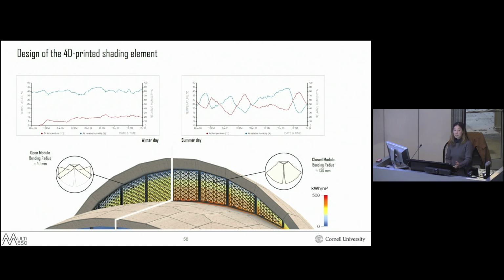So how do we program shading for different seasons using humidity reactive materials, which I've been talking about? In temperate climates, such as in the southern parts of Germany, but also here in the northeast US, there's a reliable link between temperature and humidity. Taking a look at a typical winter day on the left, you can see that the humidity in blue remains quite high, while the temperature in red remains low. But on a typical summer day, there are more daily fluctuations in temperature, but the humidity always remains with this inverse relationship. And so we designed our shading elements to curl and open when humid and flatten and shade when dry.